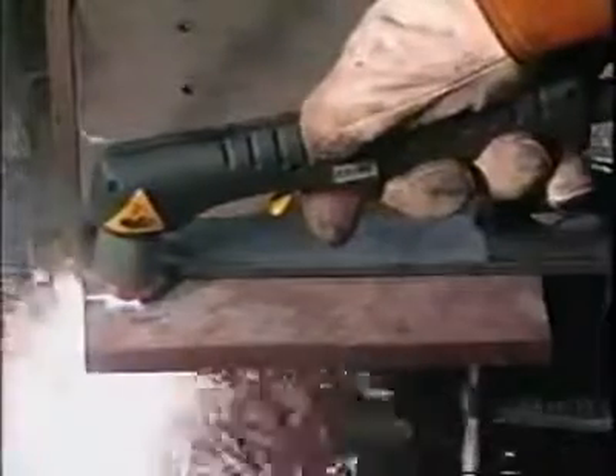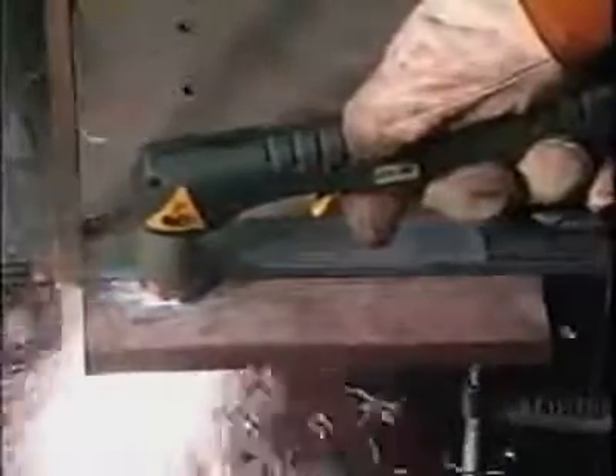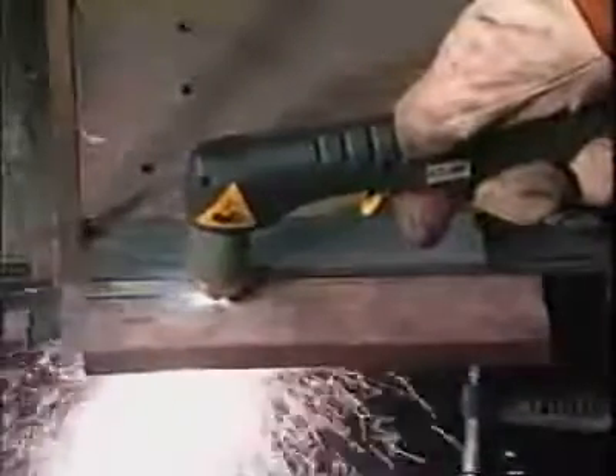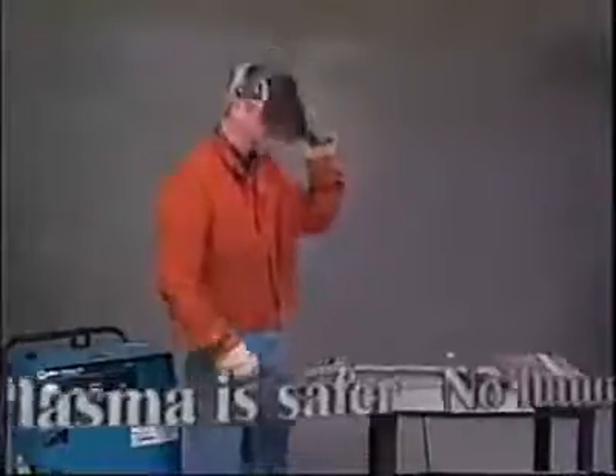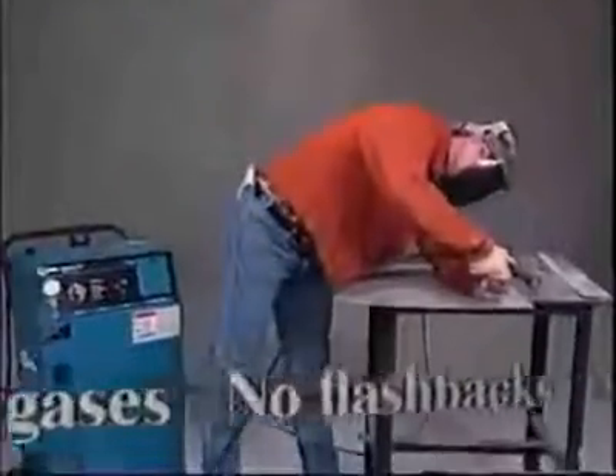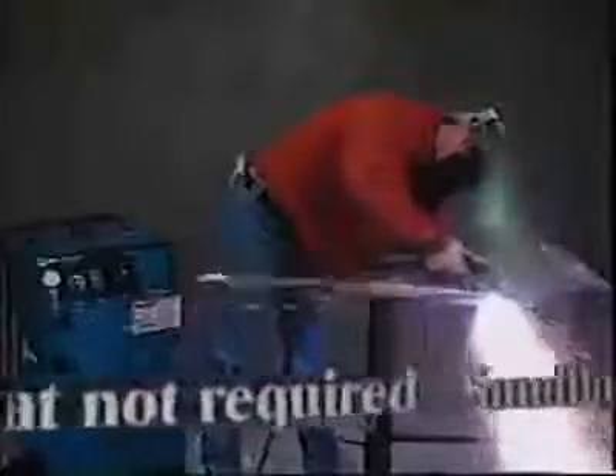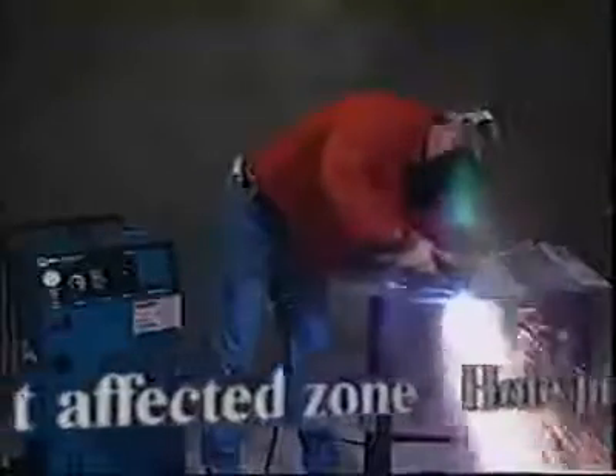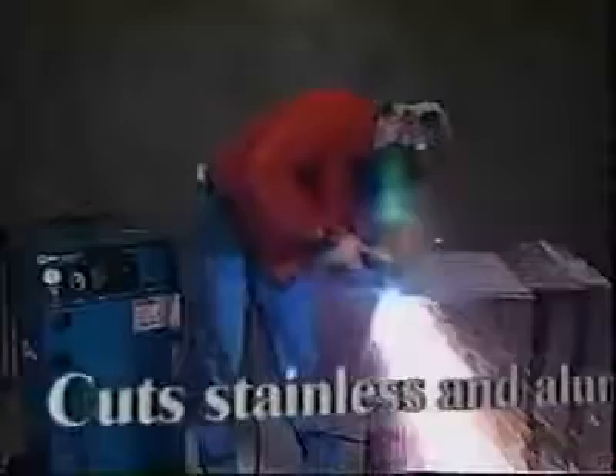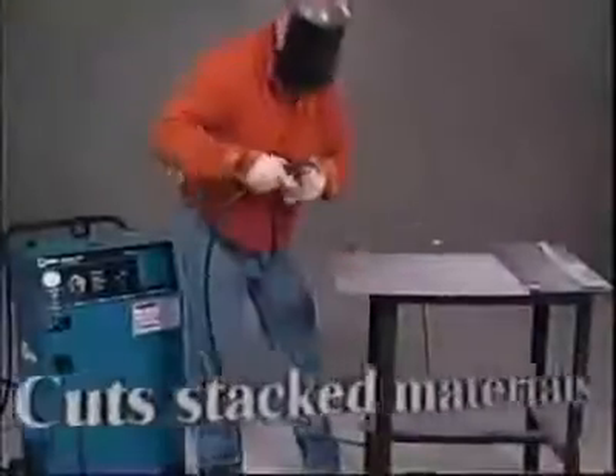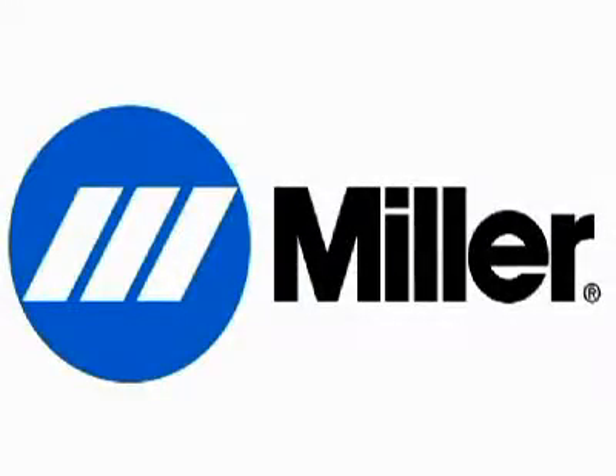Air plasma cutting will probably never completely replace oxyfuel, but plasma's advantages should be considered for your cutting and gouging applications. Plasma is safer. There are no flammable gases. There are no flashbacks or danger of explosion. Plasma cuts faster. Preheat is not required. Plasma cutting leaves a much smaller heat-affected zone. Plasma hole piercing is easier. Again, because preheat is not required. Plasma cuts stainless and aluminum. In fact, any electrically conductive material. Plasma cuts stacked materials. The Miller Spectrum series of air plasma cutting systems includes a system that may well provide the solution to most of your metal cutting requirements.